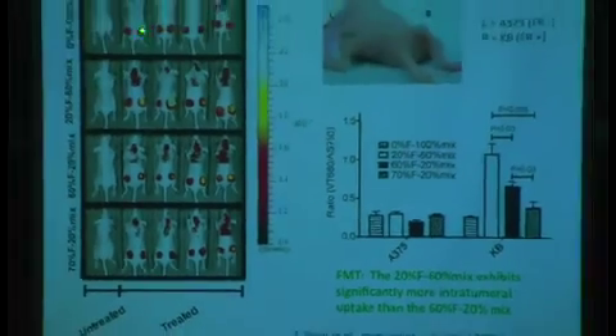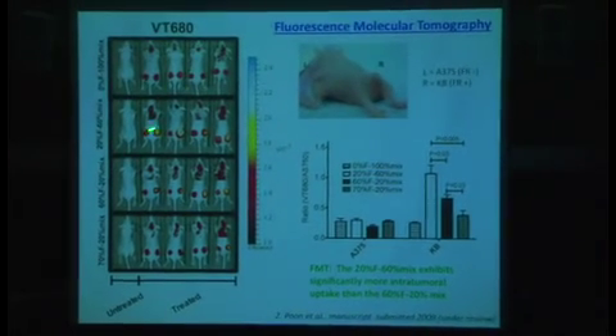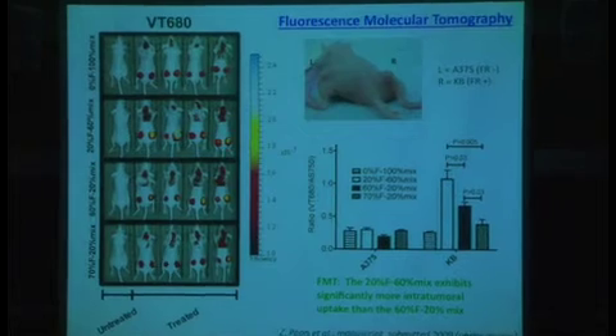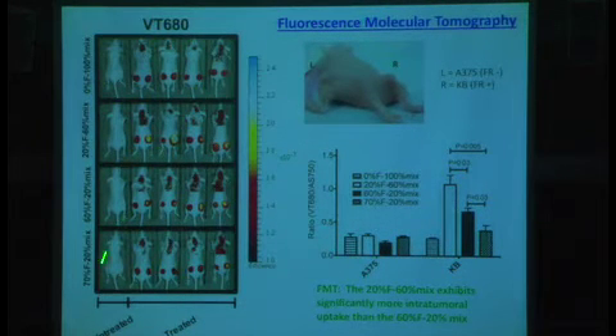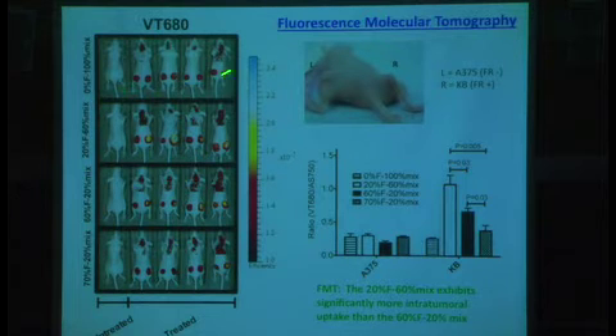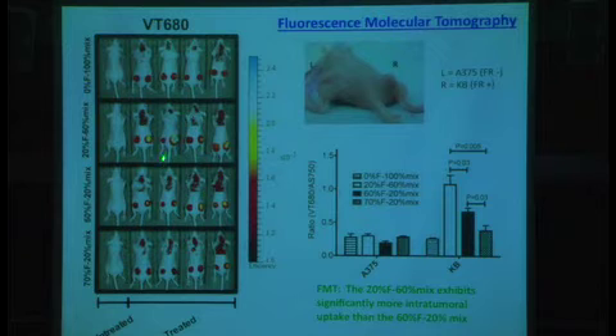So we can actually look at this in vivo. We've done fluorescence molecular tomography to do this. We have on the right flank of the mouse a tumor that's a KB tumor, so it overexpresses the folate receptor. On the left flank of the mouse, we have a non-folate presenting tumor. And as we can see, as we move from 0%, this is after 24 hours, so we're beyond the enhanced permeation and retention effect at this point, we see very little accumulation. With the 20% folate system, we actually see, in these yellow and blue colors, indications of much higher amounts of concentration of the drug nanoparticle in the tumor.